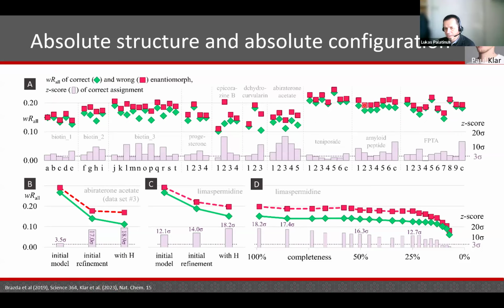The red point is the R value for the wrong enantiomorph. The green point is the R value for the correct enantiomorph, and you can see that in most cases the differences are so clear that simply by looking at the R factor we can determine the absolute structure reliably. On top of that, it's possible to do a statistical evaluation of the differences. These are these weak pink bars, and they show you the reliability of the absolute structure determination, which in most cases exceeds the statistically significant level of 3 sigma.